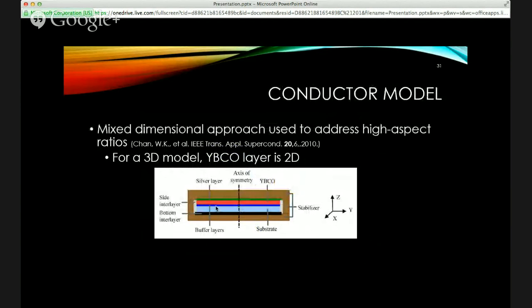Okay. So breaking that down even further, when you have a superconductor, you never just have it wound. It's called a conductor or a coated conductor, and that's because the superconductor itself is surrounded by additional layers to provide support. So in the case of YBCO, it's an oxide, so it's brittle. So you have to surround it by different layers in order to increase the stability. So for this case, it's a copper stabilizer that sits on the outside.